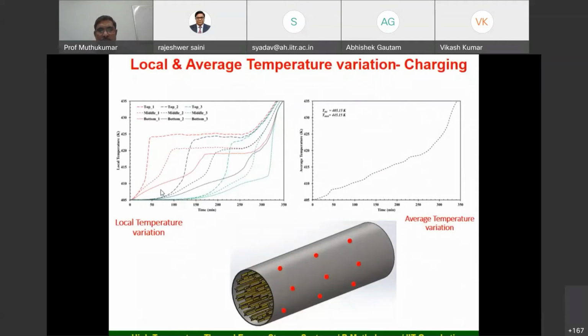So here you can see the typical charging of the system. It's a melting phenomenon. Here is the local temperature versus the time, and the flat line shows the melting of the PCM, because the melting will be at near uniform temperature. Basically here we are supplying the fluid from left to right, and the red one is the left portion, and the middle one is the middle one. The last green line is the last one. And there are 3 thermocouples, the top, middle, and this is the bottom.